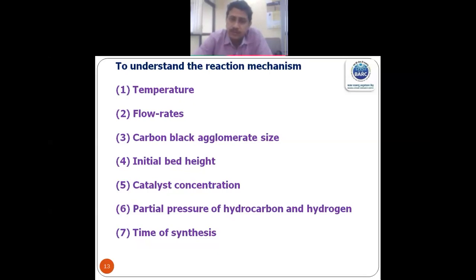and this activation energy gives us an estimation of what the rate controlling step is. Because if we don't know the rate controlling step, we cannot scale it up. From lab scale to industrial scale, if we want to scale it up, we need to understand the reaction mechanism and find out the rate controlling step. So temperature gives us the first hint of what may be the rate controlling step. If the activation energy is high, it may be chemical kinetic control. If it is low, it is diffusion control.